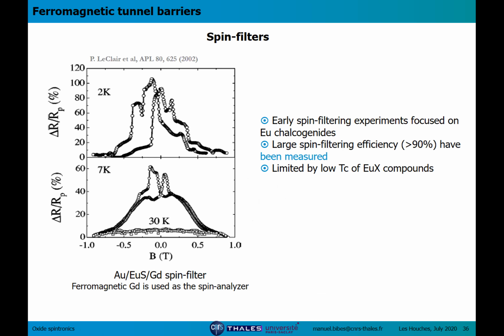This is another result in which this is a spin filter junction. So here we don't have superconducting aluminum. Gadolinium is used as the ferromagnetic electrode. Gadolinium is a ferromagnet, as you know, with a relatively small spin polarization, but its growth was compatible with europium sulfide. So you can see these TMR curves reaching about 100%. They look a little bit strange, but they were reproducible from that paper. And their non-orthodox shape, the authors argue, is due to domains being present and the displacement of domain walls in the ferromagnetic barrier. The TMR is about 100%, and a spin filtering efficiency of about 90% can be extracted from these numbers.